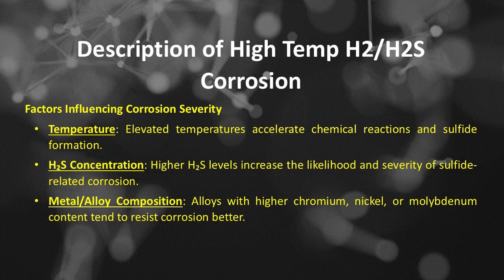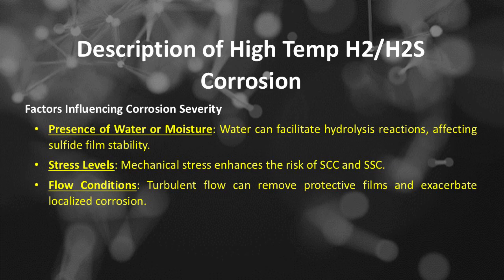Factors influencing corrosion severity of high temperature hydrogen or H2 and hydrogen sulfide or H₂S include temperature. Elevated temperatures accelerate chemical reactions and sulfide formation. Hydrogen sulfide or H₂S concentration: higher H₂S levels increase the likelihood and severity of sulfide-related corrosion. Metal or alloy composition: alloys with higher chromium, nickel, or molybdenum content tend to resist corrosion better. Presence of water or moisture: water can facilitate hydrolysis reactions, affecting sulfide film stability. Stress levels: mechanical stress enhances the risk of SCC and SSC. Flow conditions: turbulent flow can remove protective films and exacerbate localized corrosion.